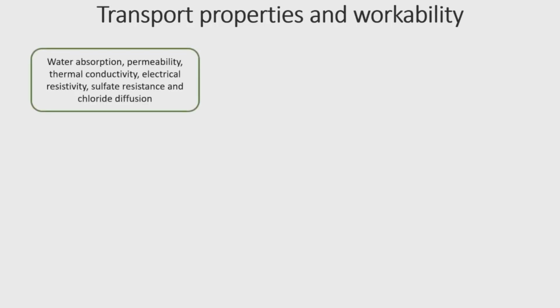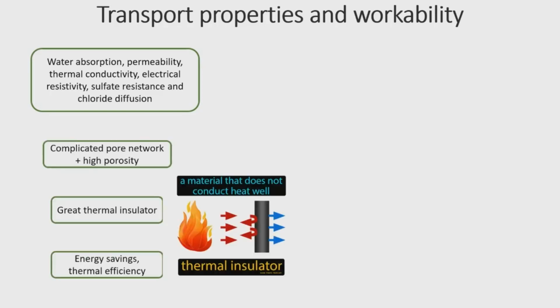In the context of transport properties and workability of biochar composites, in cementitious composites several transport properties are important. To name a few, we have water absorption, permeability, thermal conductivity, electrical resistivity, sulfate resistance, and chloride diffusion. As we have exposed before, biochar presents a complicated pore network, regardless of the biomass feedstock, which contributes to diffusion effects and entrapment of contaminants. And its low thermal conductivity and high porosity allow it to be considered as an insulating agent.